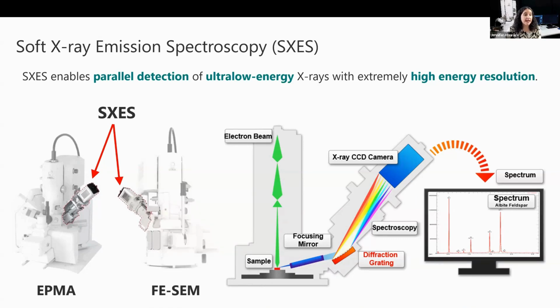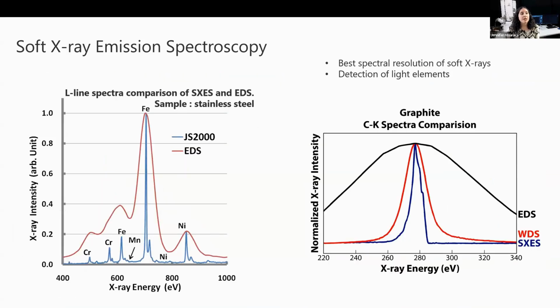It provides parallel detection of low energy X-rays using a focusing mirror, a high energy resolution diffraction grating, and a CCD camera to acquire a spectrum that is similar to an EDS spectrum. This unique design offers the best spectral resolution of soft X-rays available on any commercial SEM or EPMA. It can not only detect light elements, including lithium, but can even detect trace amounts of these light elements in the 100 ppm range.